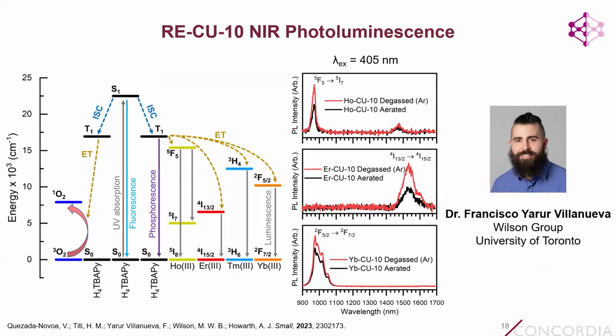And so this data was collected by Francisco Yarur Villanueva, who was a PhD student in Mark Wilson's group at the University of Toronto at the time, and he's now a postdoc. So in order to probe whether this linker to metal energy transfer was actually taking place, we needed to see if we could observe the near-IR emission coming from these lanthanoid elements. And so we do, in fact, see that from holmium, erbium, and ytterbium Cu10, confirming that this energy transfer is taking place. And that can be a competitive pathway with the generation of singlet oxygen.